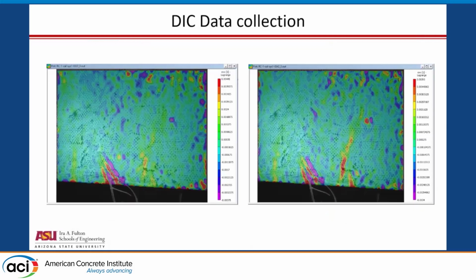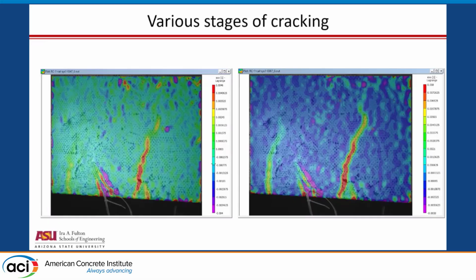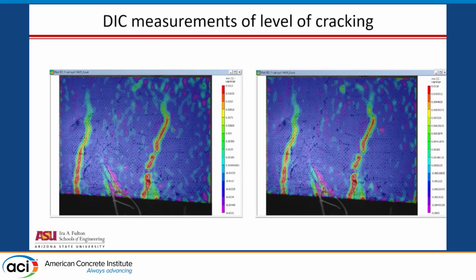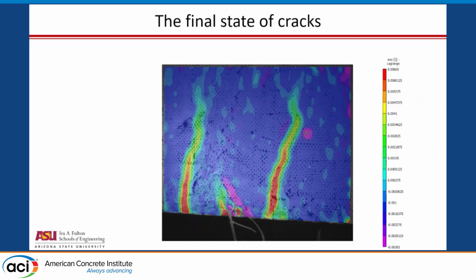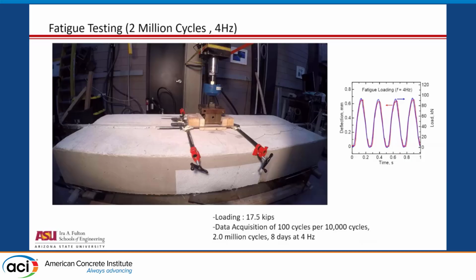Now, we can use the digital image correlation data to show us that with the fibers, we're getting multiple cracks happening very close to one another. And that distributes the cracks. You have a much more uniform deformation. And this allows us to assume that our deflection is not going to be localized. So the potential for failure in terms of durability is much less. Although I'm not so worried about corrosion because of the humidity or salt in Phoenix, Arizona, but still these are very comforting.